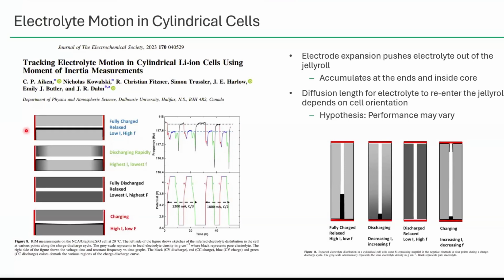This work was done with taking cells in a horizontal orientation, and a lot of cell testing is done where you would fixture, say, a cylindrical cell horizontally on a board and put it into a cell cycling device. But even in the same lab, you may have a chamber that holds cells vertically. Especially when we think about this moving of electrolyte in and out of the jelly roll, pumping electrolyte, does that have an effect on cell lifetime? If I test my cell vertically versus horizontally, am I going to get different pieces of information?